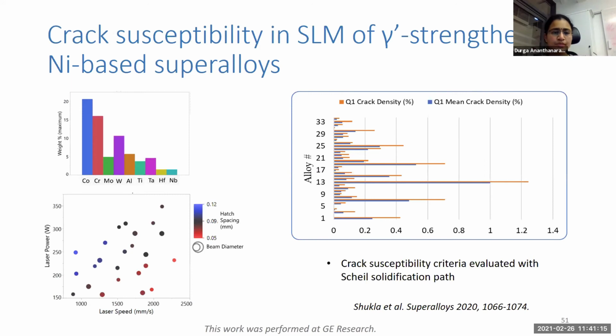So what we did in this project was we had a bunch of high gamma prime content nickel-based superalloys, and all of them were put through the same set of process conditions. So you have this consistent set of data. And then the crack density was measured for all of these different alloys. So we could really compare them, like one of them is more susceptible to cracking than the other. And we used the Scheil solidification path again to evaluate the criteria that I showed in the previous slide.